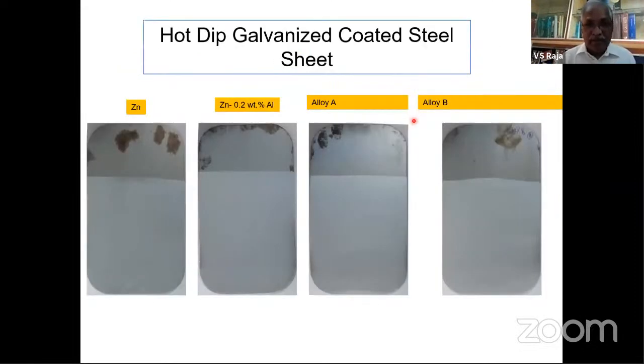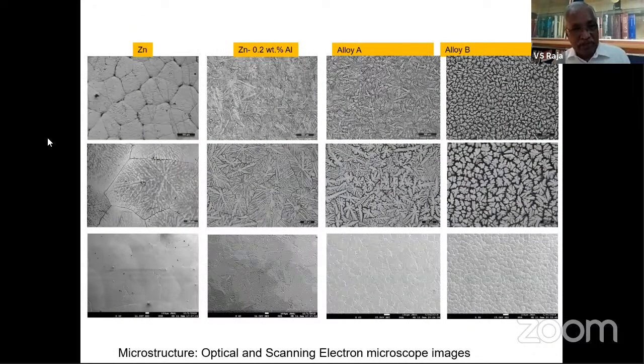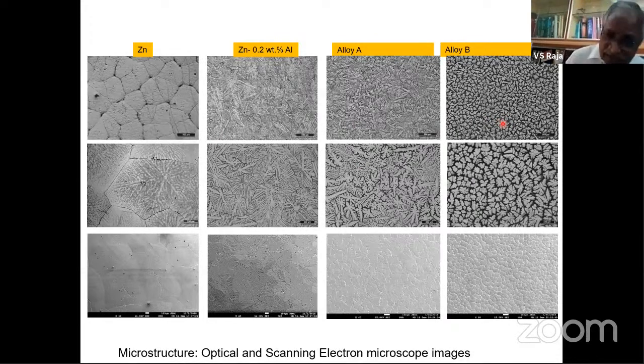How does it happen? This is the kind of visual picture that you see here, but see them in the microscope. You see a significant change in terms of the microstructure in these alloys. And this is what we call grain size refinement taking place. And this refinement has given enormous resistance to corrosion. That means you can imagine that for the same thickness of the coating, life is increased by 5 times, 6 times. A wonderful thing to save resources, and it gives you better properties actually.